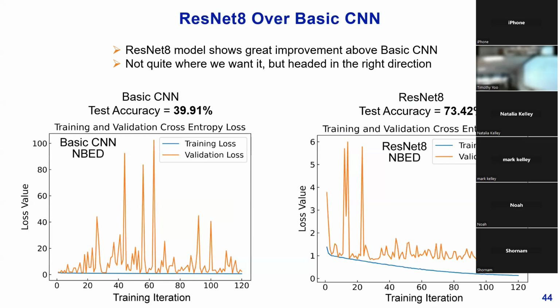And so we see already that this ResNet 8 model that we've developed is almost a factor of 2 better than the basic CNN on average in terms of the test accuracy, so its performance on unseen data. While this is definitely heading in the right direction, again, it's still not quite where we wanted. This validation loss, although it doesn't fluctuate as wildly as before, remains stagnant around a certain value while the training loss continues to dip. So we can see that it's still overfitting despite our best efforts.